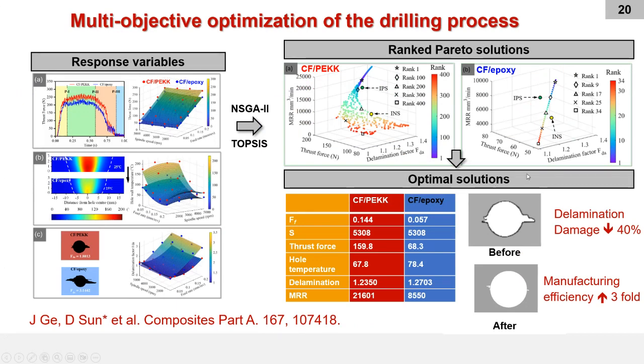The experimental work presented in the previous slides provided the crucial data for us to conduct our pioneering research on multi-objective optimization for CF reinforced PEKK composites. We created the first hybrid algorithm combining NSGA-II and TOPSIS. This allowed us to obtain Pareto solutions and rank them based on their proximity to the ideal solutions. And this optimized solution, after experimental validation, is shown to reduce the hole delamination damage by 40% and improve the machining efficiency by up to threefold.